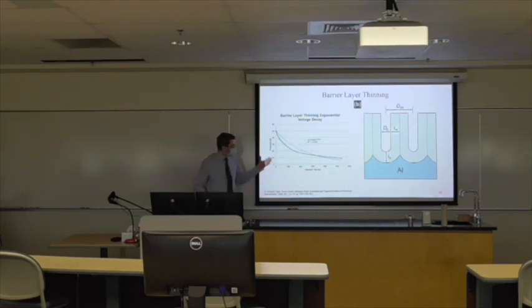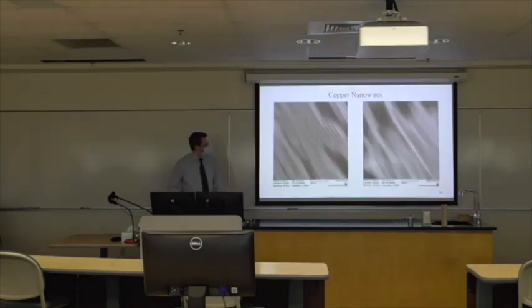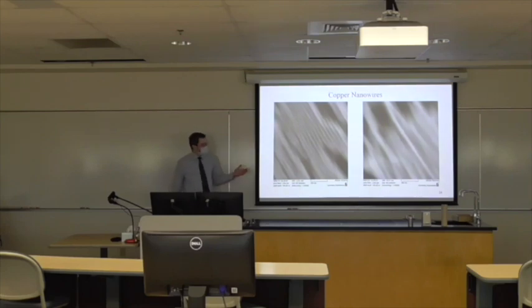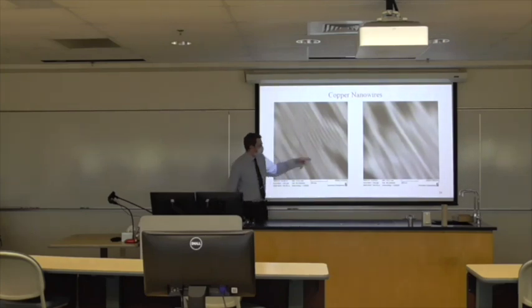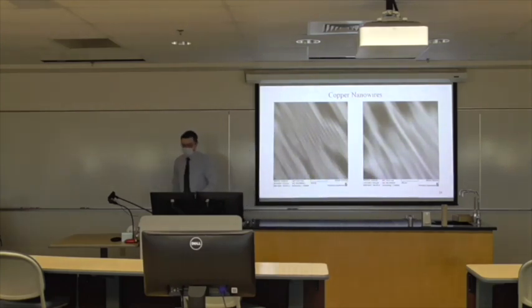So we did this, and we were able to deposit copper using a copper sulfate solution into the pores. We get wires that look like this when we partially dissolve the aluminum oxide template away from it. We can see that there is the same sort of ordering of the pores of these wires, as well as that the wires are exhibiting this 60 nanometer in diameter property, which indicates that it's from these sorts of pores, and that we can use these pores to make these sorts of wires.